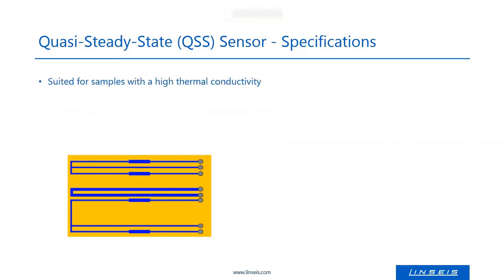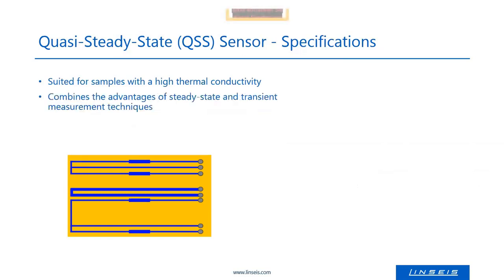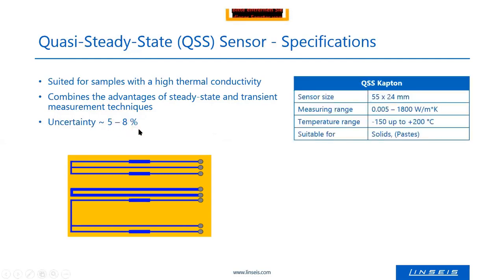The specifications are listed here. It is designed and suitable for high thermal conductivities. It combines the advantages of the steady state and transient measurement techniques in one sensor. The uncertainty is quite good for thermal conductivity devices. It's not as good as with the THB sensors, but it's still between 5% and 8%, which is better compared to laser flash, for example. The range is practically all, the whole range of thermal conductivity you can measure.